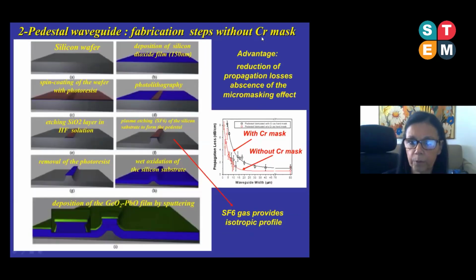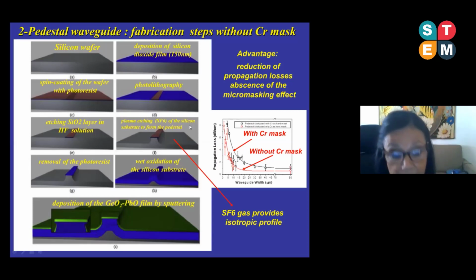When we do not use a chromium mask, we have some advantages. Here are the steps for this fabrication: the silicon wafer, deposition of silicon dioxide film, spin coating of the wafer with photoresist, photolithography, etching of the silicon dioxide, plasma etching of the silicon, removal of the photoresist, wet oxidation of the silicon substrate. Like the other case, the last step is the deposition of the material. Unlike the other case, here we have 2 etchings, one for the silicon dioxide and the other for the silicon. And the advantage in this case is that, as we do not use a chromium mask, we are not going to have the micromasking effect.